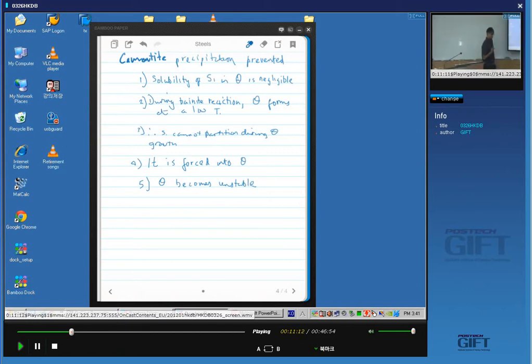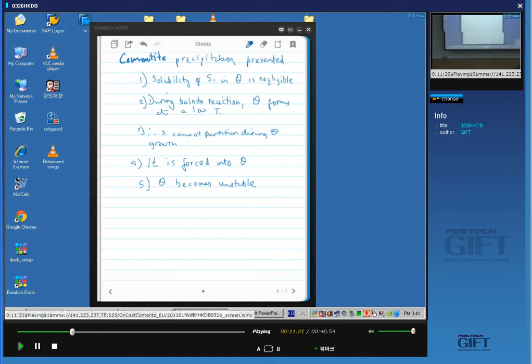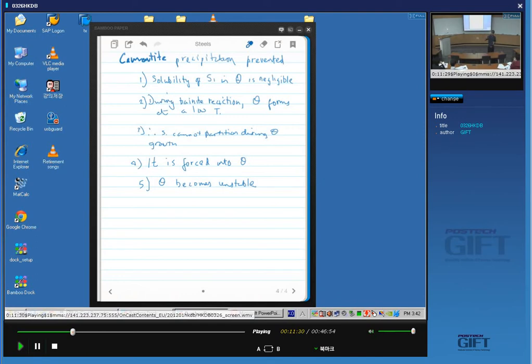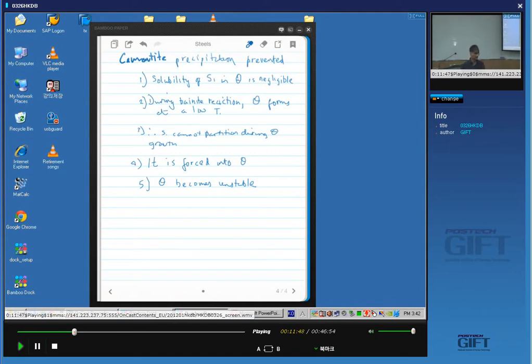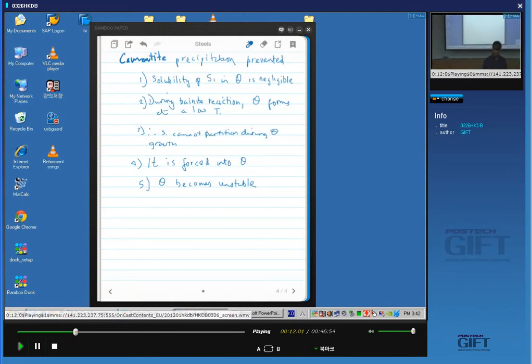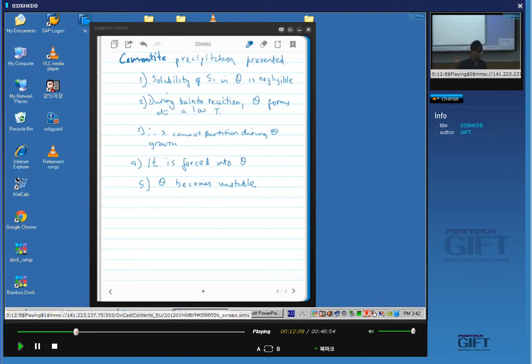The important point is that if cementite formed at a high temperature, above about 600°C, then silicon could partition out, and there's no problem precipitating cementite. So in the same steel, if you form pearlite at around 600°C, silicon slightly retards the transformation but doesn't stop cementite precipitation. You need two conditions: silicon must be forced into the cementite lattice, which only occurs when cementite forms at a low temperature. That is the mechanism by which silicon stops cementite precipitation from austenite. Aluminium probably works the same way, though we don't have the same kind of evidence.